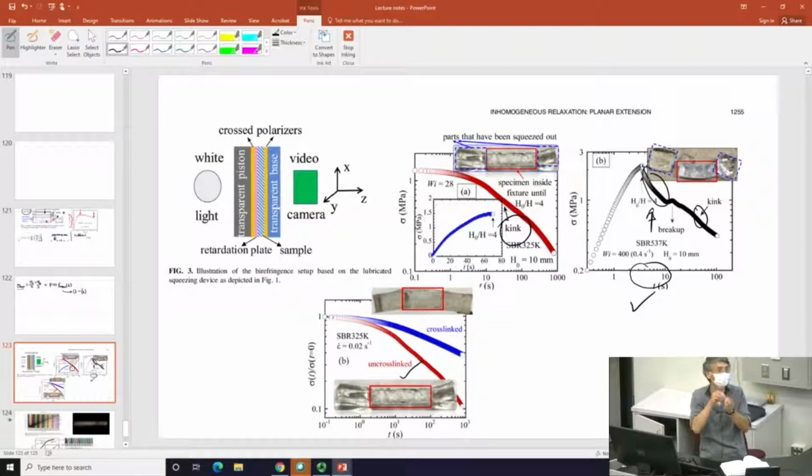That's why the re-swelling, or recoil back, is not uniform everywhere. So it gives you wrinkles. And just to test that's the scenario, you can have your sample cross-linked to prevent that failure. And the sample is smooth in that case. Okay?